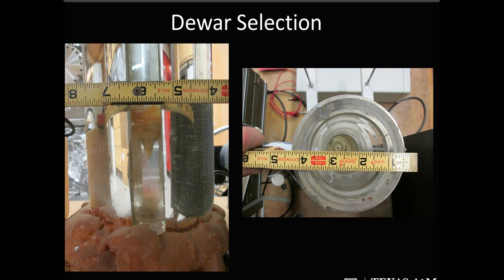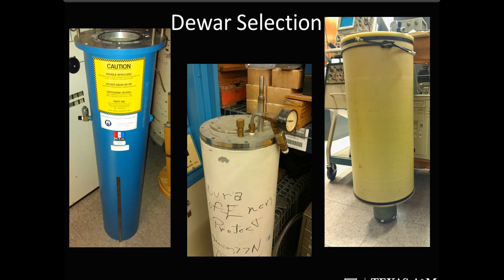We started out looking at a glass Dewar. It offers little attenuation to X-rays, but its sample space is very small, and the energy of the X-rays goes with the radius of the sample. So we looked at some other candidate Dewars. The two on the left have very large sample spaces, but they're aluminum, so they offer a lot of attenuation to X-rays. And the one on the right that we finally arrived at is a biomedical Dewar. It's going to allow us to get the sample down in this nice little tail. It's fiberglass, so it won't attenuate X-rays much.